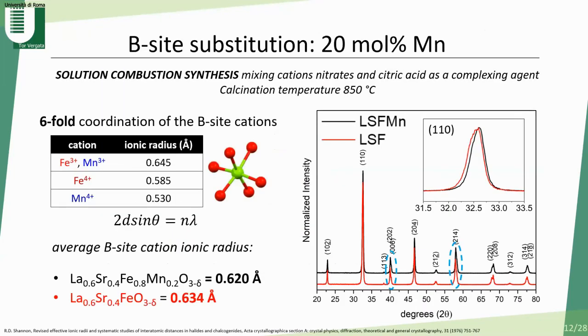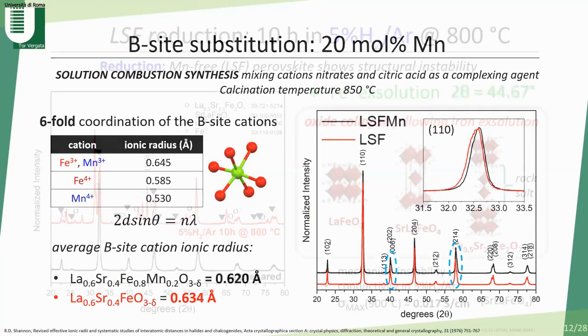Our compounds were synthesized by solution combustion synthesis and calcined at a temperature as high as 850 degrees C. Here is the XRD diffraction of the manganese substituted and manganese-free compounds. As we can see, the main peak is shifted toward higher angles, which means that the unit cell is decreased due to the lower ionic radius of manganese compared to iron.